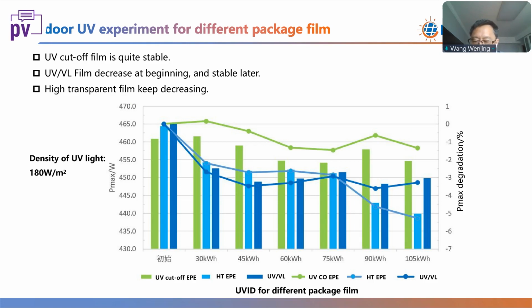But the indoor experiment is quite different. Here we use a UV light density of 180 watts per meter square. The UV cutoff film is quite stable, but the high transparency film and the UV to visual film reduce at first. After a longer time, the high transparency film reduces further, but the UV to visual film becomes stable. But why does this happen in the indoor experiment?